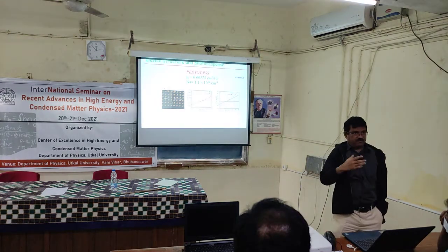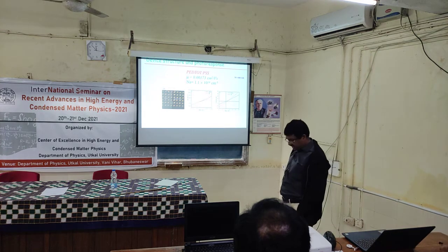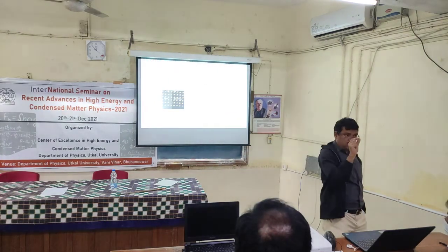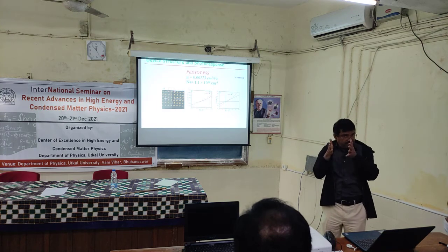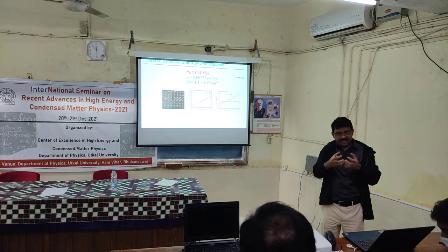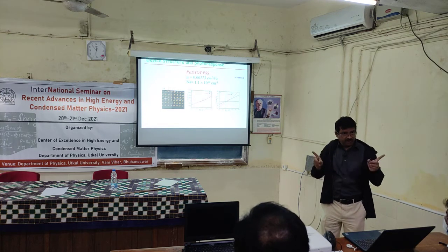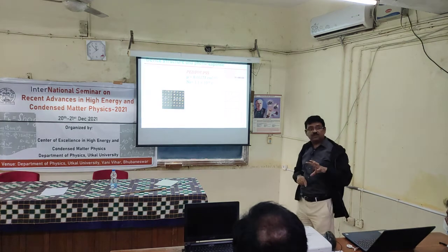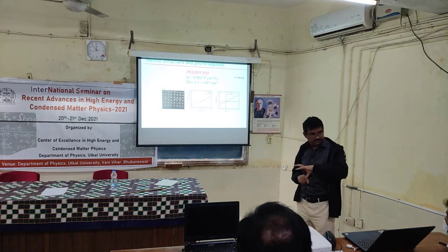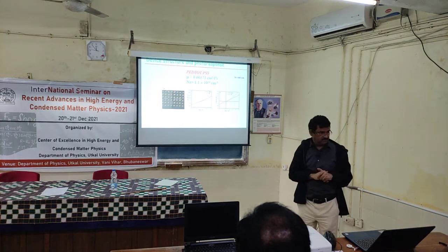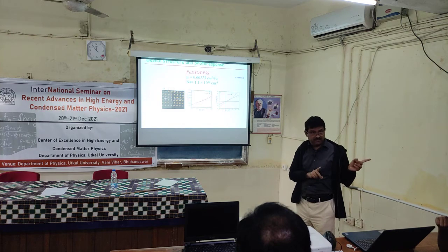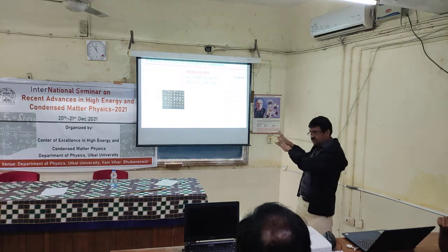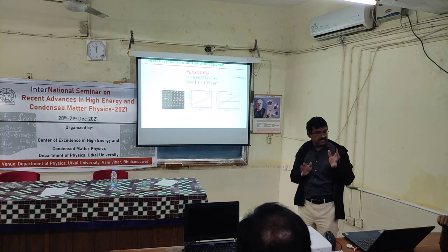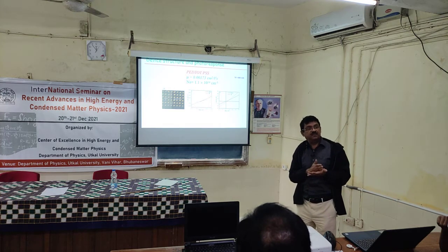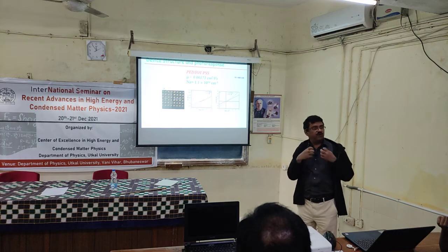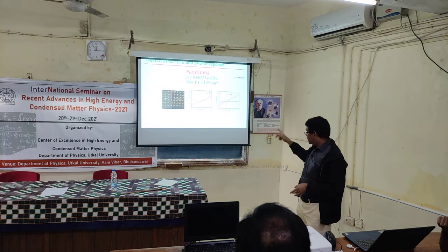If you have come across the photovoltaic cell, you get a photocurrent at zero bias, because when you shine light there will be a built-in potential. That built-in potential attracts the electron and hole towards opposite sides, and you get a photocurrent. Keeping that in mind, people have talked about self-powered photodetection in the case of a PN junction. I don't have to apply a bias, but I still get a photocurrent, as you see here, which is not possible in the case of a linear device. You have to apply a bias. So the beauty of the PN junction based device is that you can have self-powered photodetection. Basically you are able to eliminate your power supply. That's what people have also done.